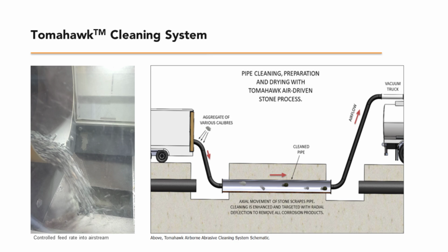Through its initial pilot program, PUC evaluated 2 cleaning systems and found that cleaning times could be significantly reduced using the Tomahawk cleaning systems. Tomahawk uses a vacuum truck connected to the main to generate sufficient airflow and speed to fly abrasive stone in the pipe. Axial movement of the stone scrapes the pipe wall with a result similar to sandblasting.